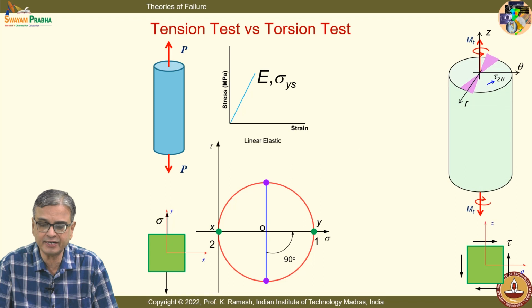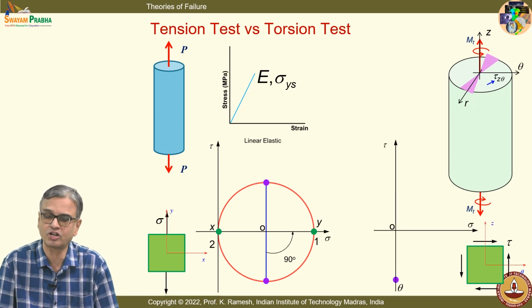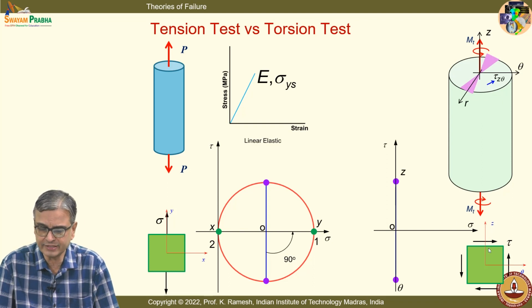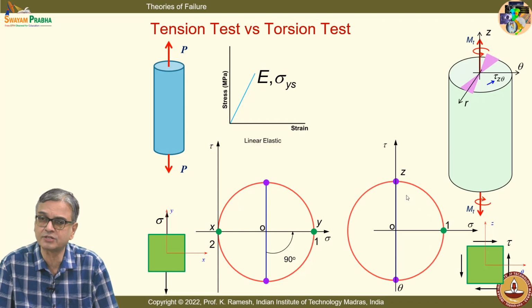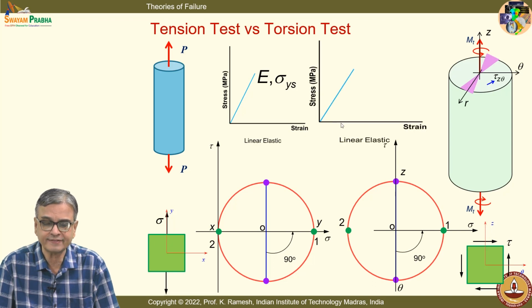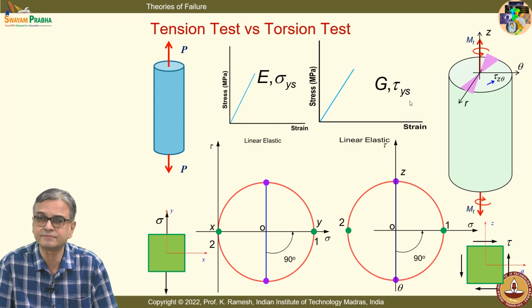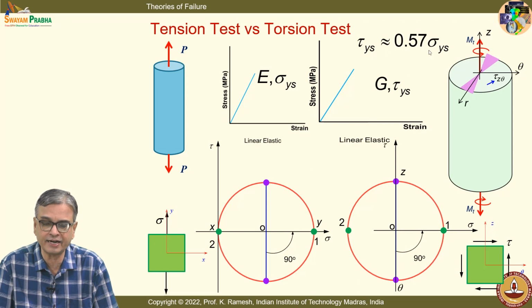See, the accuracy achievable in a tension test is much more than in a torsion test. The torsion test is also difficult to do, and you have a state of pure shear, and you know how to draw the Mohr circle for the pure shear stress state. From a torsion test, you essentially get the shear modulus and the yield strength in torsion. Fine, for shear stress, instead of sigma ys, you call this tau ys. And you know the slopes will be different, because G is E by 2 into 1 plus nu. So, the slope will be smaller than what you have here. And there is also an interrelationship, which is approximate, about 0.57 of sigma ys.